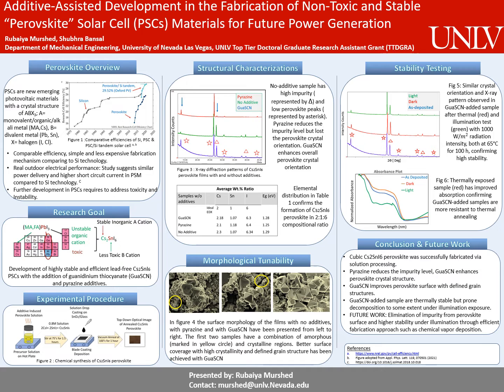To further understand the stability of the perovskite films, we measured absorbance that is presented in figure 6, which shows thermally exposed films in dark condition have improved absorbance, while the light exposed films have significantly reduced absorbance. So we suggest that the guanidinium thiocyanate added samples are highly stable under thermal annealing but prone to decomposition under